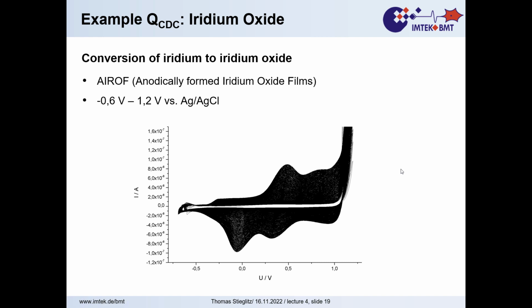In the case of iridium oxide, you remember that fancy material that does not like to decide if it's 3 times positive or 4 times positive, depending on the potential. We get this very characteristic bump shape, and here we overdid that a little bit. By overdoing that, you get continuous processes that increase the amount of charge transfer. That is good on one hand, and that is called an anodically formed iridium oxide film. That works in salt water. You do that, and the salt water reacts with the iridium.